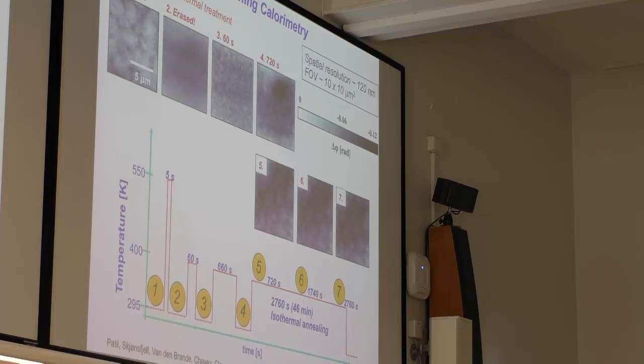And during this evaporation, solidification, etc. process, some structures are formed in the film. Some morphology is formed, and that's what you see here. The next thing we did was, so this was at room temperature, right? Measured at room temperature, image number 1. Then with this remarkable heating device, we could go up to 550 Kelvin. You can take the temperature difference here and estimate how long we used to go there. It's instantaneous, right? Straight up into the melt. We stayed in the melt for 5 seconds, and then cooled down at the same rate back to room temperature.